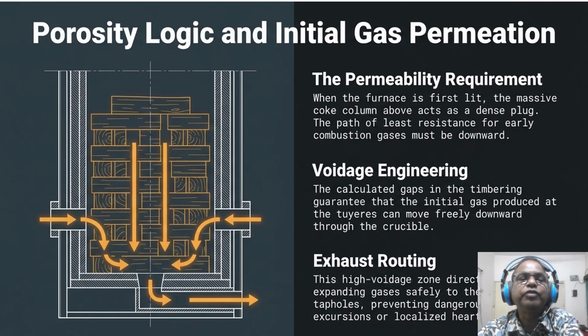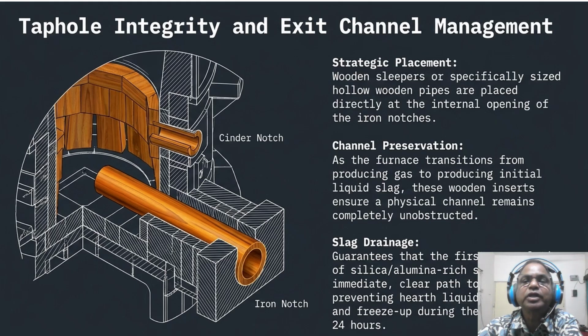So if you fail to maintain this porosity logic, the gas will channel up to the wall, causing localized overheating and a dangerous pressure spike. So this is about thermodynamic safety. We are engineering a path for the furnace to breathe while it's still too cold to establish its normal upward flow. To ensure this gas and eventually slag can actually leave the vessel, we must manage tap hole integrity. Our next slide is about tap hole integrity and exit channel management.